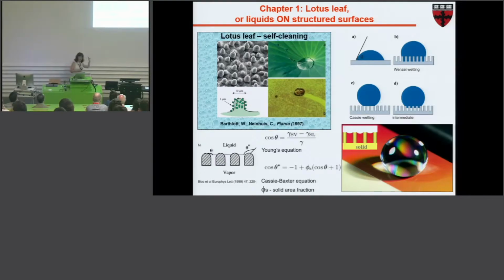What is interesting, this is a hydrophobic surface. So the lotus leaf is hydrophobic. It is super hydrophobic. Now, just the same way as a hydrophobic surface being structured becomes superhydrophobic, if you have a hydrophilic surface being structured, it becomes superhydrophilic, which is that water on that surface, even though it had a contact angle below 90 degrees but not zero, when it is structured, will be nearly zero. It means that it will form a continuous film on the surface. So structure is extremely important. Probably in this particular case it is the dominant factor that will give you either superhydrophobic or superhydrophilic properties.